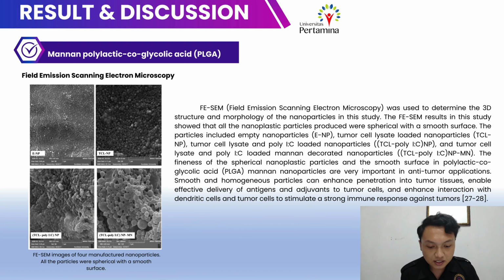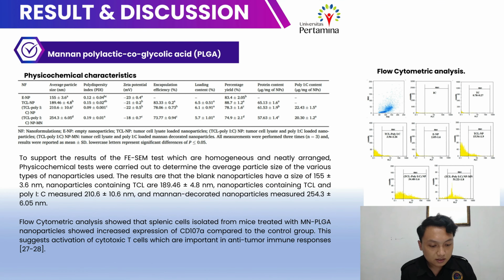To support the FESEM result, physicochemical characterization is performed with the following result. The size increase in Mannan decorated nanoparticles was due to the addition of Mannan. However, all sizes remain suitable for uptake by dendritic cells. The polydispersity index (PDI) for all nanoparticles was in an acceptable range, with a slight increase in Mannan decorated nanoparticles.